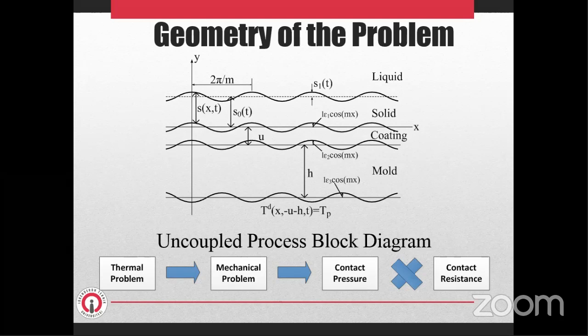After a time, the liquid forms a solid shell of thickness S(x,t). S(x,t) defines the instantaneous position of the freezing front and it consists of two parts, S0(t) and S1(t). S0(t) indicates the mean shell thickness and S1(t) denotes the amplitude of the developing periodic variation at the moving interface due to non-uniform heat extraction. Thermal and mechanical problems are uncoupled at the shell coating and coating mold interfaces.